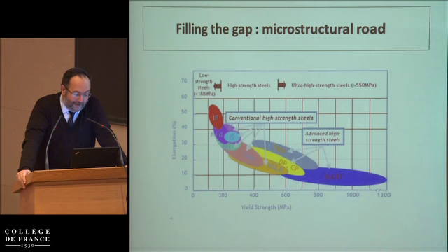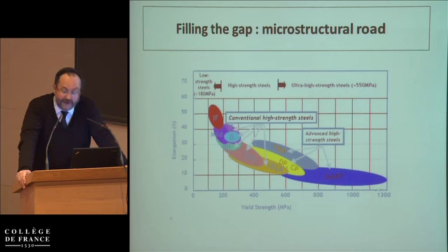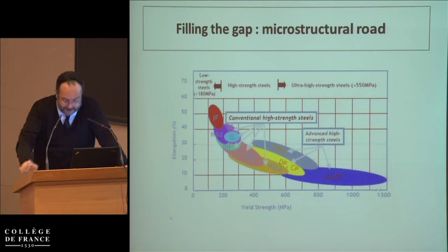And here you find that a material which has a high ductility usually has a low yield strength, like the case of steels, and a material with high yield strength has generally a low ductility, which is the case of martensitic steel. And the whole dream of scientists in steel metallurgy is to escape from this banana curve and try to develop material which would have a good combination between ductility and strength.